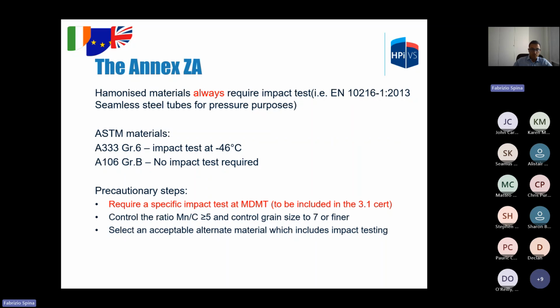For ASTM materials, the situation is different. For example, the A333 grade 6 has an impact test at minus 46 degrees, but for A106 grade B, no impact test is required by the standard. This is not compliant with what PED asks. So precautionary steps must be used. The most common option that we recommend is to require a specific impact test at the minimum design temperature. And the result of this test must be included in the 3.1 certificate for the material.